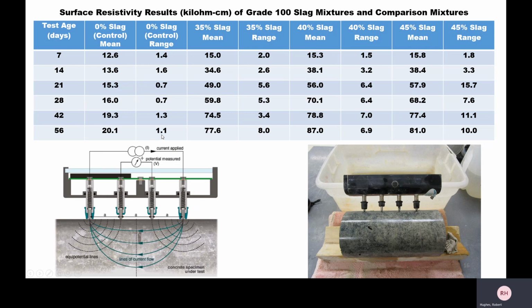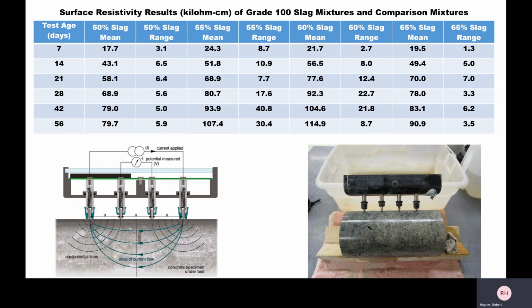So here, obviously, we're very good with ranges at a control level, and our ranges get a little higher at the higher substitution levels. But you'll definitely see an increase in 56-day SR throughout each substitution. Let me go over to the 50 to 65%. And you'll see here at 60%, our mean is 114.9. And past that, at our 65, it did decrease. So we'll talk about that a little bit more in the results section and conclusion. But we did peak at 60%.